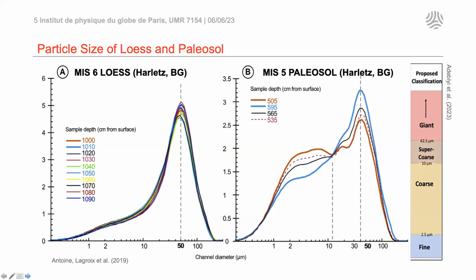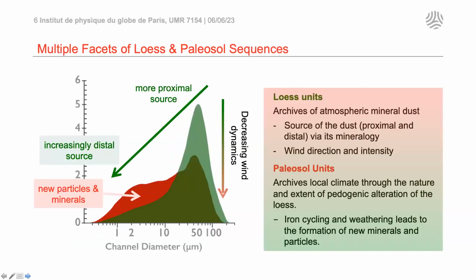The same similar coarse particles are also found in the paleosol, which is logical because it's simply altered loess, diminished obviously in total amount, and also with a very logical shift of the peak to a slightly finer median size. And the smaller particles, the less than 10 microns, are amplified in the paleosols. So if we look at these two generalized distributions and superimpose them on top of one another, it's really easy to understand that Loess and Paleosol sequences provide multiple facets of the system.